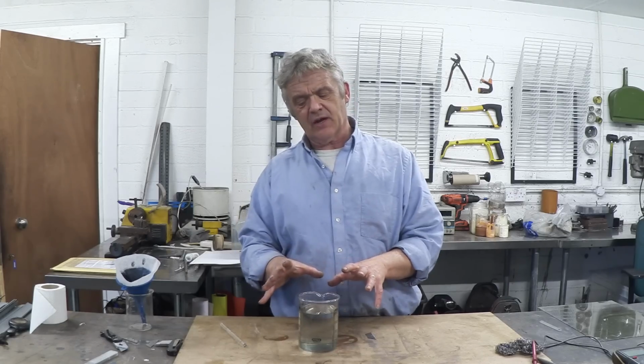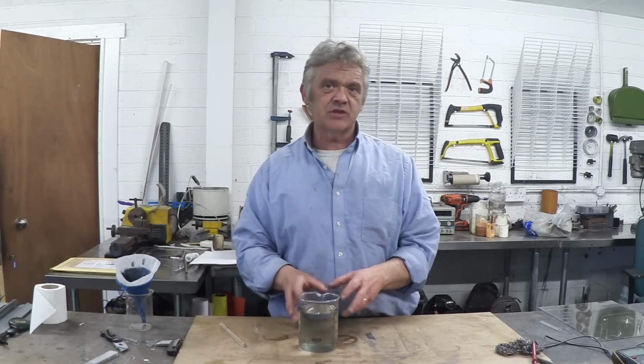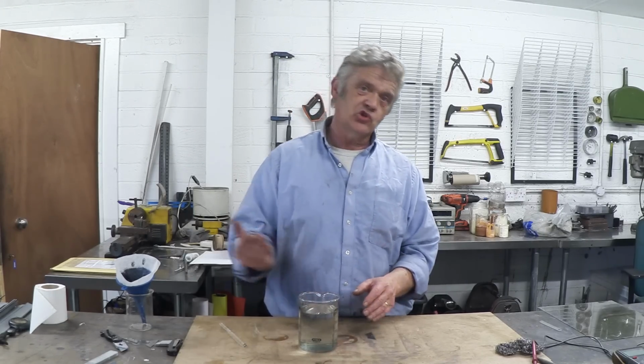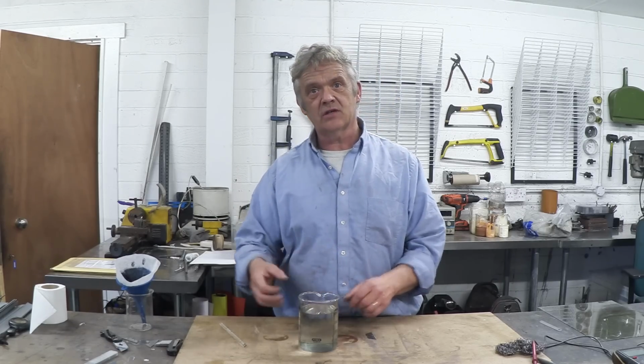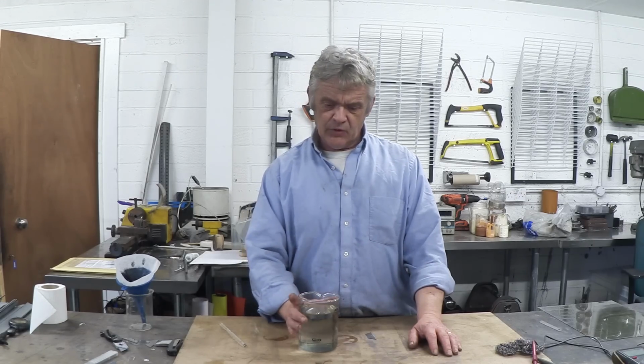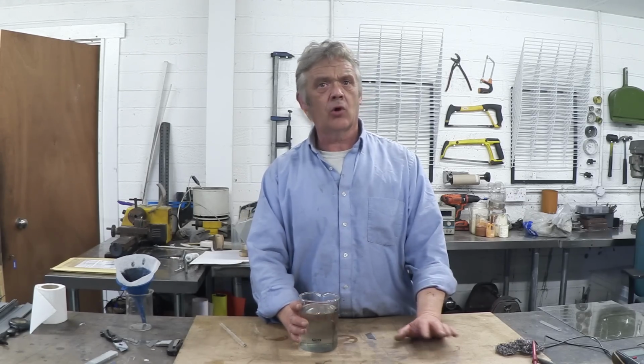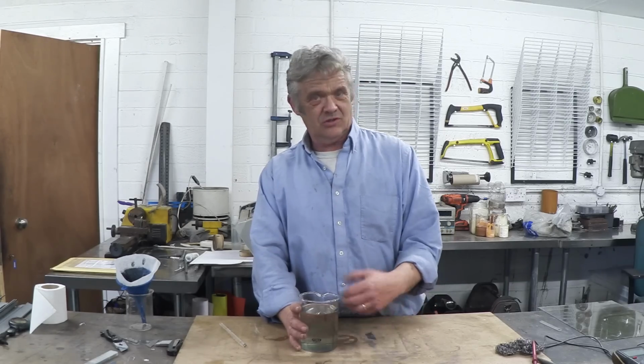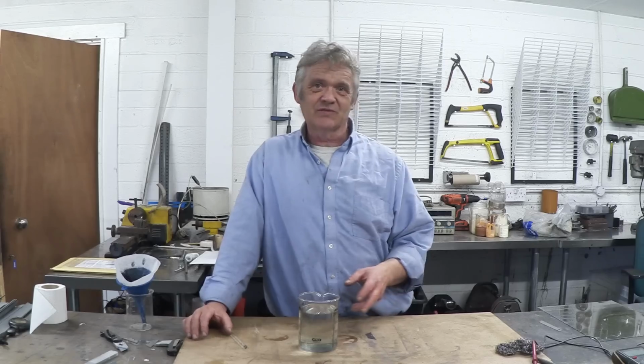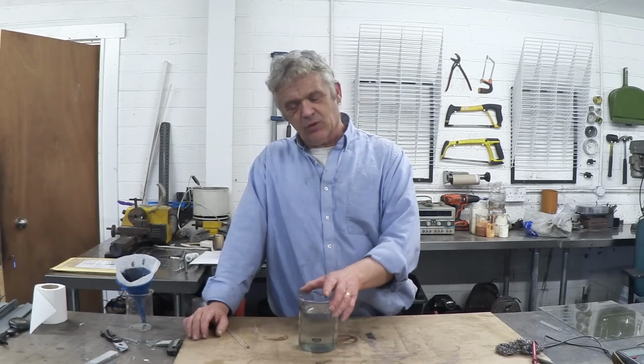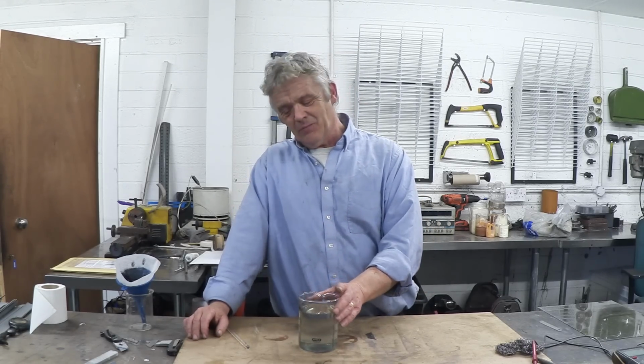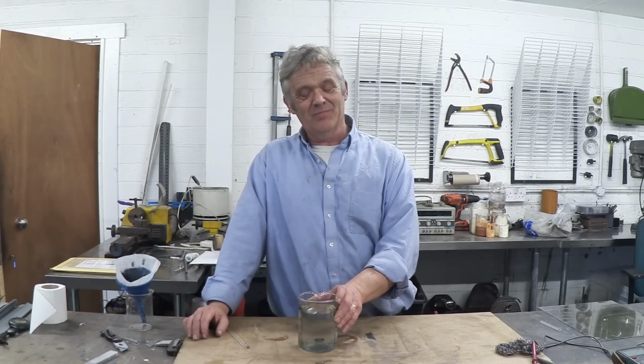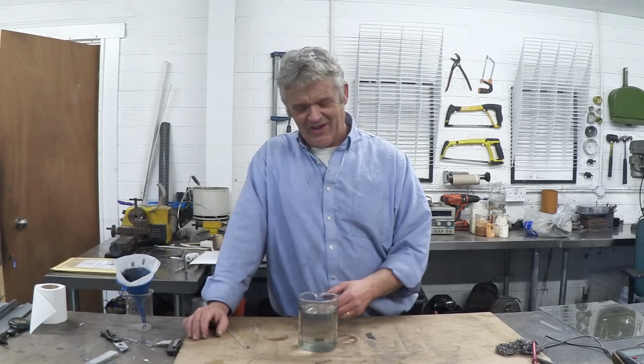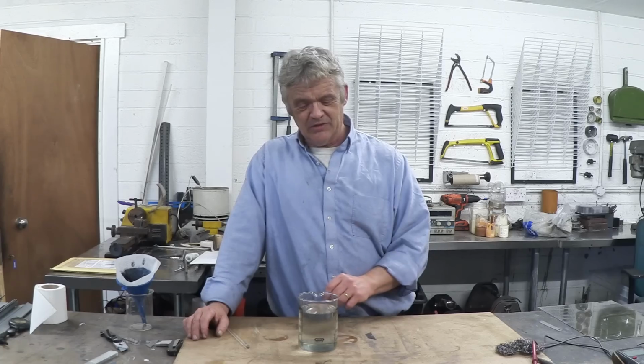But if you leave that, like I say, for 5 days, they will precipitate out as a white precipitate, and you can just refilter it again at the end of 5 days, and you'll have a pure indium tin oxalic acid mix. And those white precipitates are all of the other junk that just falls out of this particular solution. That's really, really useful, obviously. And that's one of the curious things about oxalic acid. The other thing, of course, is I can get quite close to it without being scared because it's not boiling sulfuric acid. So that's really awesome as well.